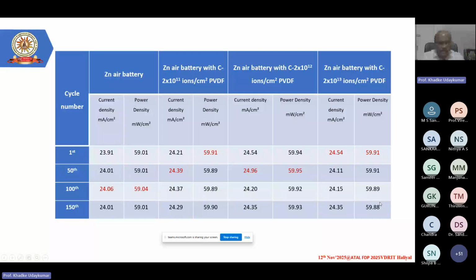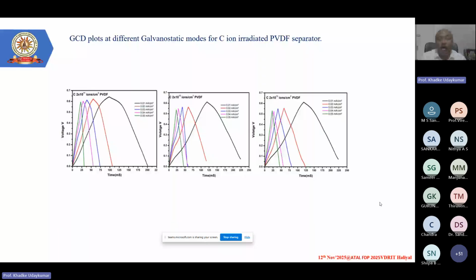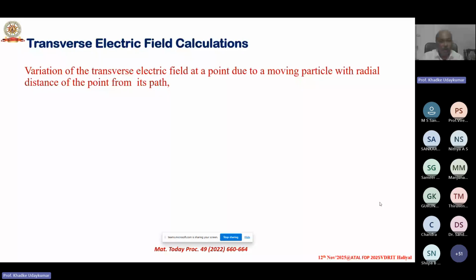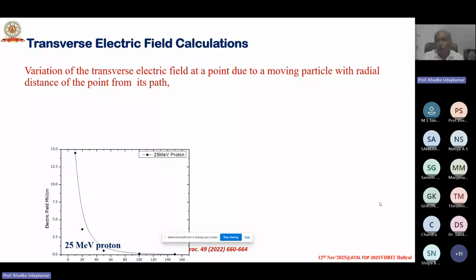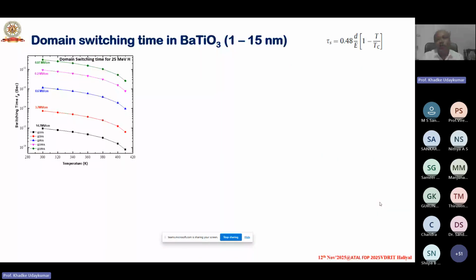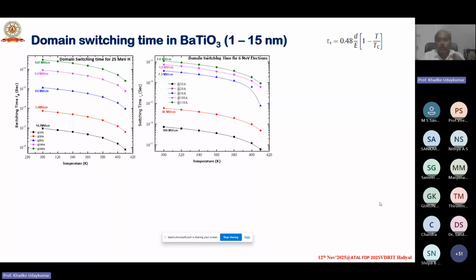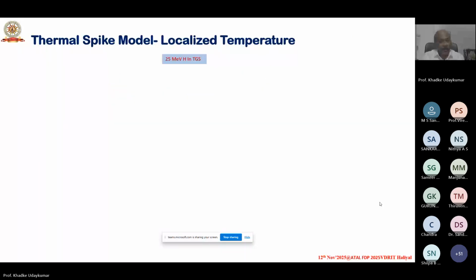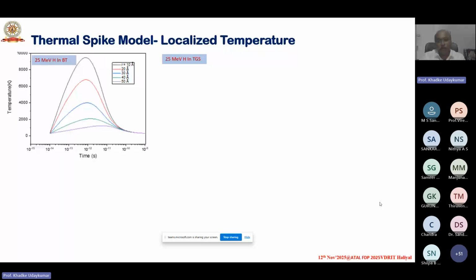These are GCD, galvanostatic charge-discharge measurements, where you can see that the area is larger, in the sense that more energy can be stored. That information can be understood from this. Let us not go deeper into that. All these are another important experiment, where we try to find out the electric field generated inside the material due to the passage of charged particles. This is electrode-free domain rotation from the ion beam, where you can use these techniques to rewrite or retrieve electronic data from the material.